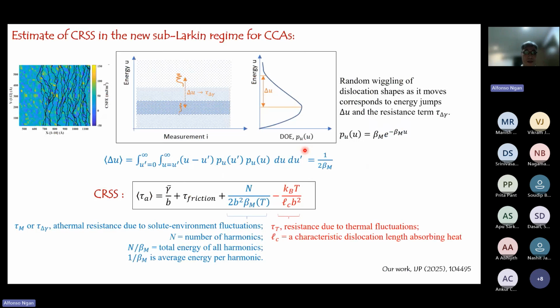And the last but not the least, given the Boltzmann distribution, that would allow us to develop an equation for the critical resolved shear stress. So the critical resolved shear stress would comprise a contribution from Fisher hardening. This is due to breakage of the short range order, as we have discussed, and usually that is a very small term. Lattice friction, that is due to Peierls stress. But the most important of all would be this athermal resistance due to the fluctuating fault energy. And in the case of high temperature deformation, we also would have a softening term due to thermal fluctuations.